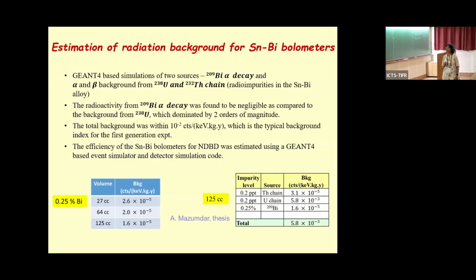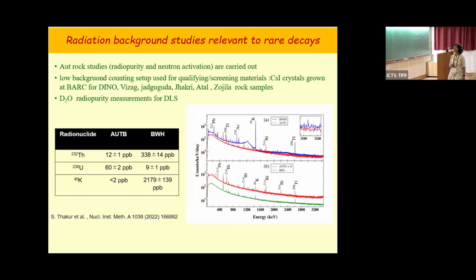So here we have some estimated backgrounds which are listed, that if you had bismuth, this is coming only from the bismuth alpha decays in the region of interest. And this is assuming thorium and uranium impurities of this magnitude, like a PPT level, what kind of background we expect. So what you see is that bismuth will not be a dominant source. It's the uranium chain which has lots of beta decays, and beta decay gives a continuous spectrum. So that is the main source of background.